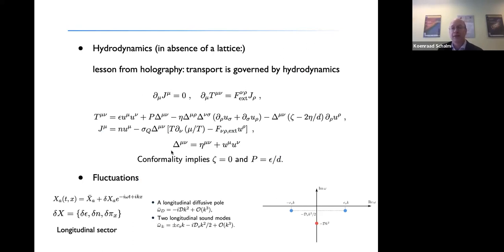So we look at hydrodynamics in a relativistic language as before, and we're studying this Gubser-Rocha black hole, which has a near AdS2 horizon, inherited from the UV system. It has a conformal scaling, so the bulk viscosity is 0, and the equation of state is just that the pressure is the energy density divided by the number of dimensions. And then the way you get this normal Drude pole is you look at the fluctuation analysis in this system, where in the longitudinal sector, that's the one that contributes to the DC longitudinal resistivity, there are three modes that couple. There's the energy density, the charge density, and the longitudinal momentum density.